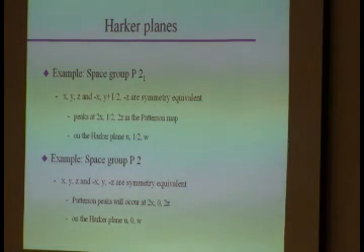Now this is pretty important because some of you asked me quite a few weeks back, okay, so we can use systematic absences to figure certain things out. How do I distinguish the rest of it? Right? Quite a few of you asked me that question. Well, here's a way. P2, systematic absences, yes or no? No, right? There's no translation in P2. P21 would have systematic absences, P2 doesn't. So, no systematic absences. Actually, you used it in your project, right?